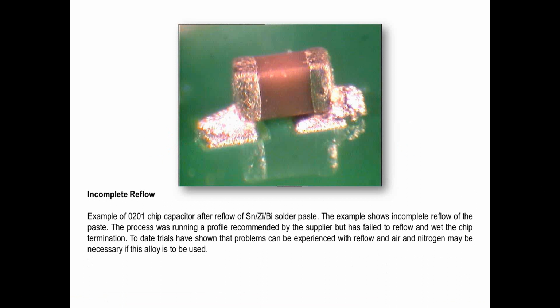These materials are not ideal to try and reflow in an air environment, and you could get this graping effect, non-coalescence of paste in exactly the same way. Now, I mentioned the tin bismuth materials because they are becoming popular again for low temperature work. And if you have experimented with the low temperature solder pastes, again, you can see this particular issue.